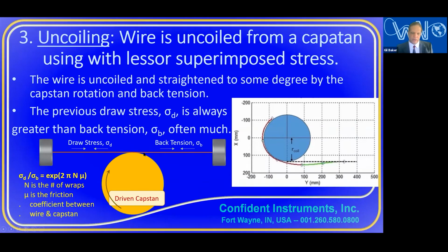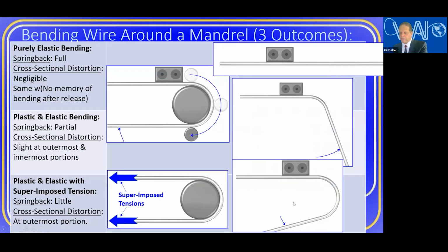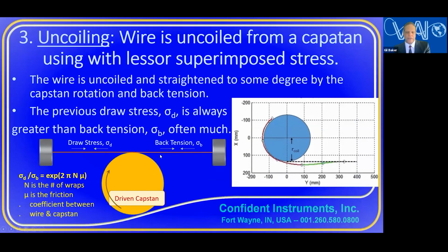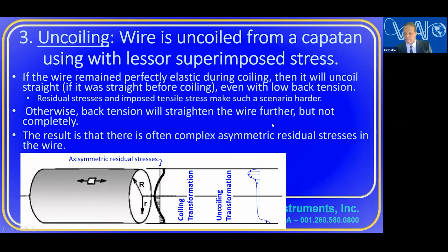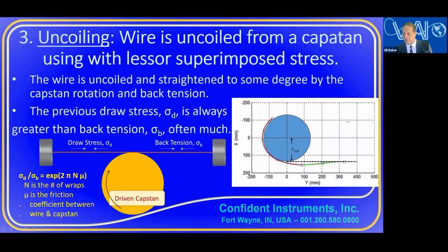Now, the next thing we do is uncoiling, number 3. So now we want to uncoil that wire, as I showed you previously, that has the shape set into it. Unless there are more devices here, we're typically just doing that with the back tension and the motor revolving the capstan. So we have to get from being coiled to straightened in some way. And when the back tension is low, you can even see the bow coming off the capstan. I have this flipped a bit, so to show it in the same light here, it would be coming off the capstan here, and then maybe coming straight right before it enters the die.